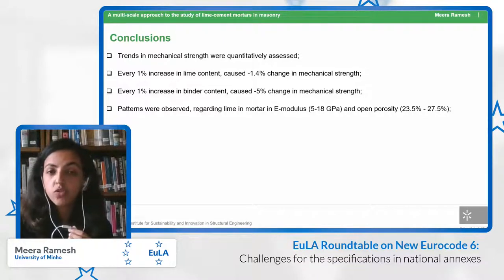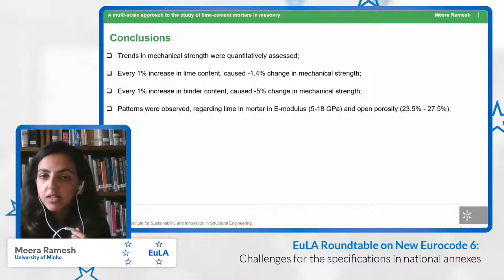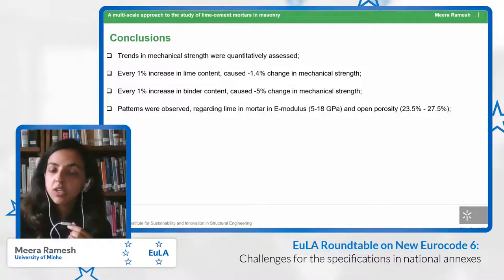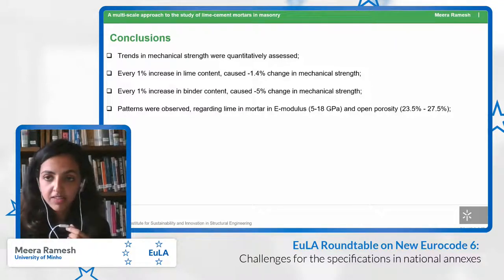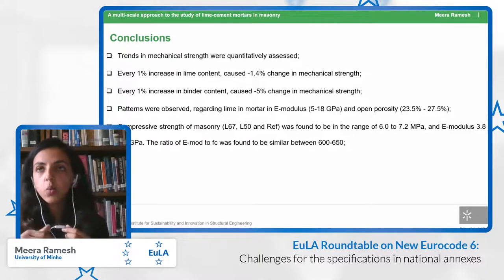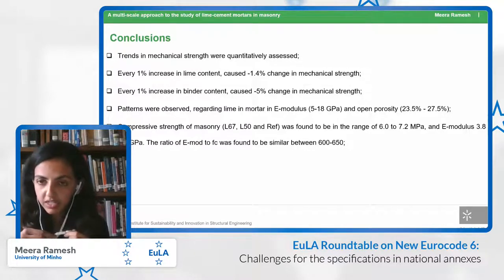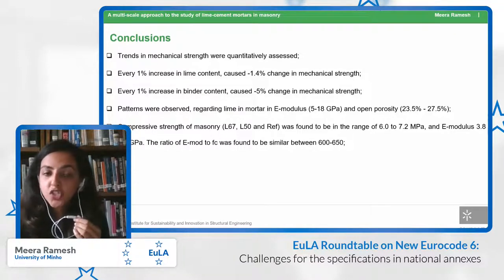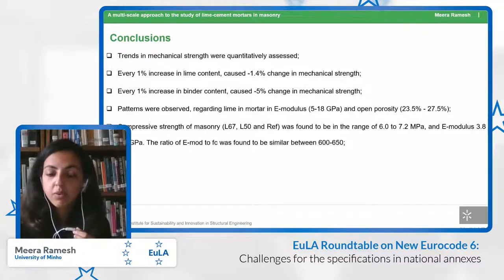In general, the values of Young's modulus ranged between 5 to 18 gigapascal, and for open porosity, it was between 23 to 27%. Young's modulus increased as the amount of cement in the mix increased, and open porosity decreased as the amount of cement in the mix increased. At the masonry level, we found that while the compressive strength of mortar is a good indicator of the compressive strength of masonry, the difference is not too much, and the strength of the brick guided the strength of masonry. This was true for stiffness as well, and the values for compressive strength ranged between 6 to 7 megapascal.